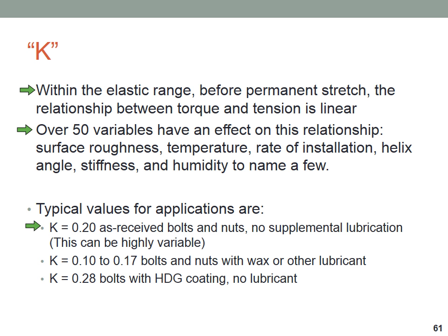Even that can change the K factor. What we typically see with fasteners that are lubricated is a lower value. 0.1 to 0.17 covers a pretty broad range of everything from wax and Teflon lubes up. A really high K factor would be if we took, for example, a hot dip galvanized bolt, nut and washer, put them together with no lubricant. The 0.28 K factor would indicate a really high level of friction.